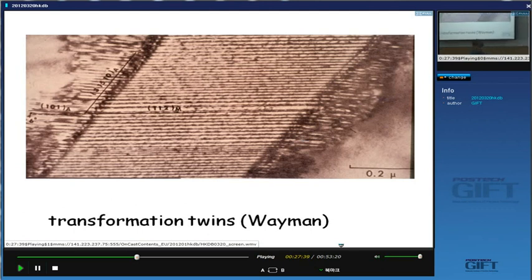And if both of these processes happen perfectly, you will not find dislocations in the martensite. Okay? So, one of the things you could have mentioned when I asked you about the characteristics of martensite is a high dislocation density. What I'm saying here is that there should be a zero dislocation density in the martensite. Yeah? And that is why we get the shape memory effect.